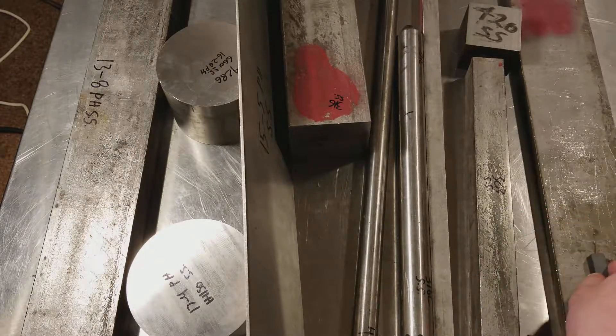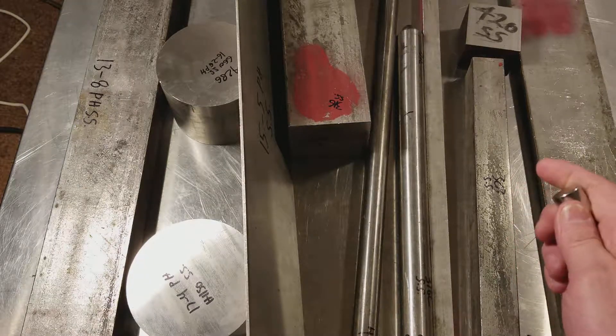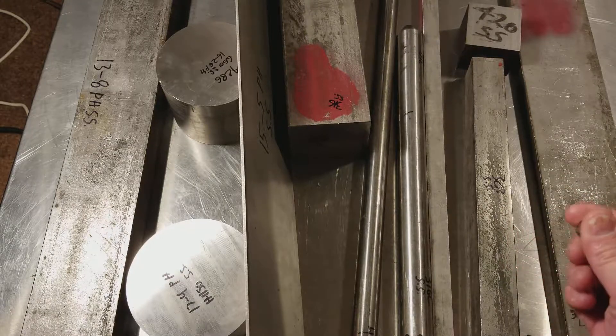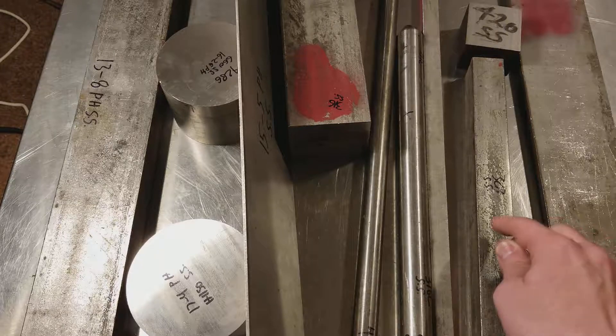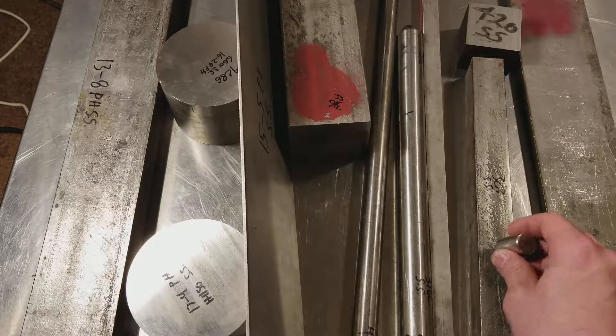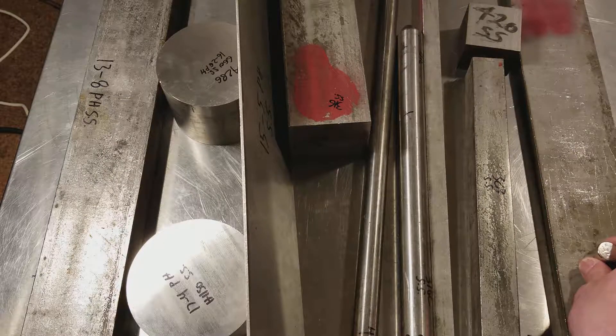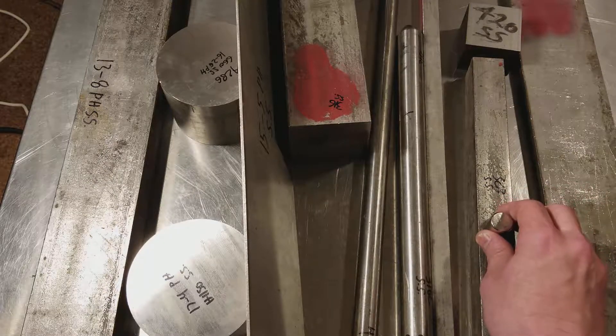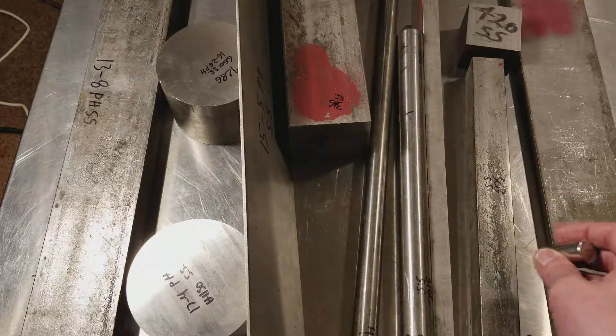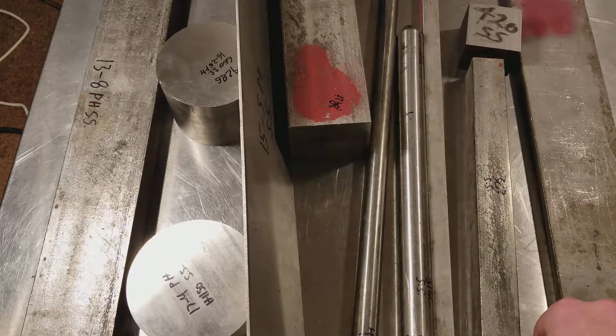Both of these pieces of steel feel like they're totally non-magnetic, but that's not entirely true. This is an N50 neodymium magnet — the N stands for the strength, and this is a high-strength magnet, like what you'd find in a hard drive. This is 303 stainless steel — we can see maybe a touch. But even with a high-strength magnet, there's basically nothing. On this low-carbon 304 — the low carbon is to make it more friendly to welding — it's actually just so slightly magnetic, and you can feel the difference. Magnetism is affected by the cross section. All this stainless steel is also sitting on a stainless steel food service table, and it's mildly magnetic — very slight.